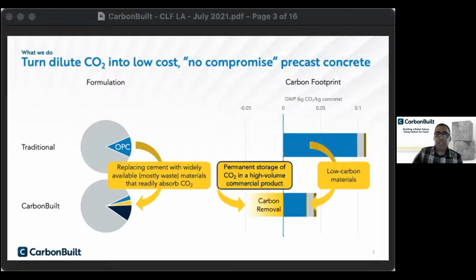The first is on the embodied carbon side of the materials that are being used. So we're reducing cement usage by something on the order of 60 to 80%, particularly in the cases where all the substitutes are waste materials. We get a reduction in any case, but it can be a quite substantial reduction in the embodied carbon. And then we're using CO2 to cure the product.